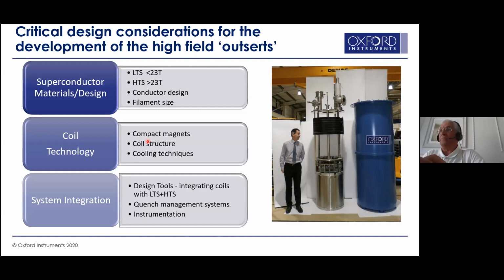Up till 2000, most of the superconducting systems we were producing were completely wet systems. For the last 15 years, we have been developing cryogen-free systems. Now, up to 14 Tesla, probably 80% of our superconducting systems up to 14, 16 Tesla are cryo-free. 20-30% are cryogen-reliant, depending on the customer needs. And if you want to go higher than 18 Tesla, the preference is still to go to wet systems for cost purposes.